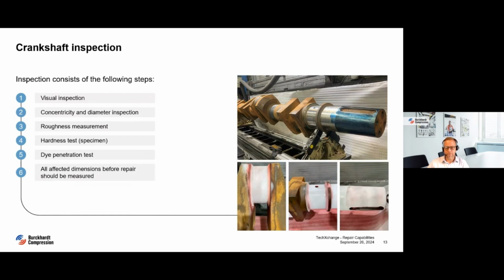Our first step after unpacking the crankshaft was our so-called step 1, the incoming inspection. We always perform an initial inspection on crankshafts upon arrival. This is the first step in our process to assess their condition and determine the necessary repairs. The incoming inspection consists of the following steps: the visual inspection, the concentricity and diameter inspection, the roughness measurement, the hardness test, the dye penetration test, and all affected dimensions before repair should be measured.